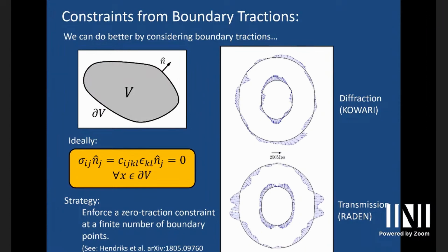Gravity is such a tiny force in comparison to what we can measure. I mean, the error bars are a good couple of orders of magnitude bigger than any stress that gravity will give you in these sort of situations. So largely speaking, there are no loads applied. It's only this internal war that's going on. And so we can apply that as a constraint: in addition to our equilibrium equation, we have constraints that can come from boundary conditions. So ideally, on that boundary, we have no surface traction.